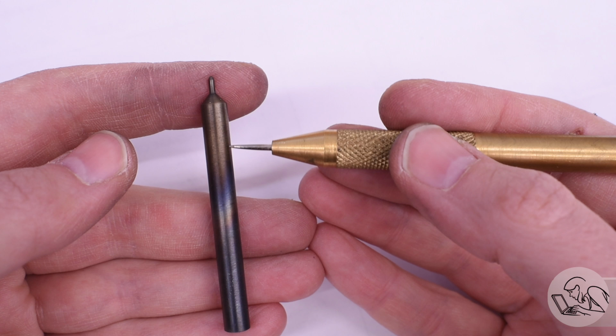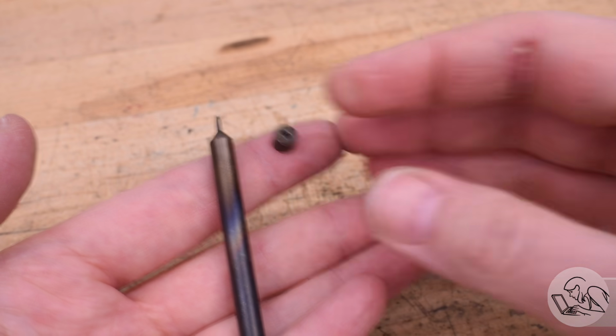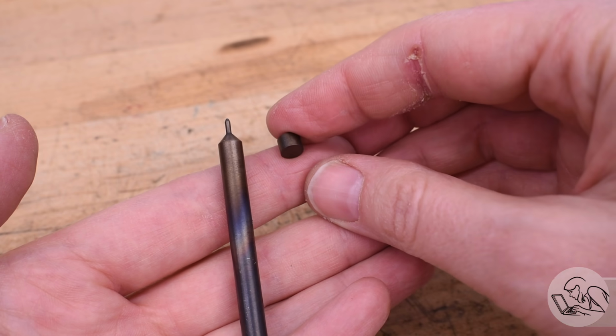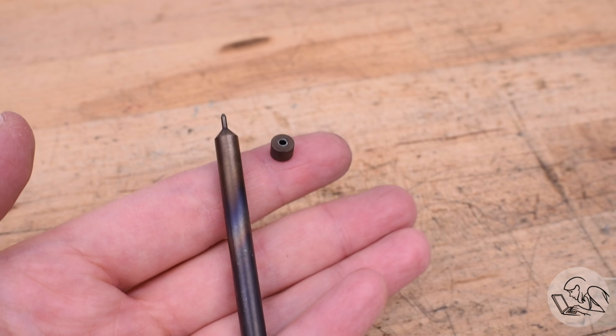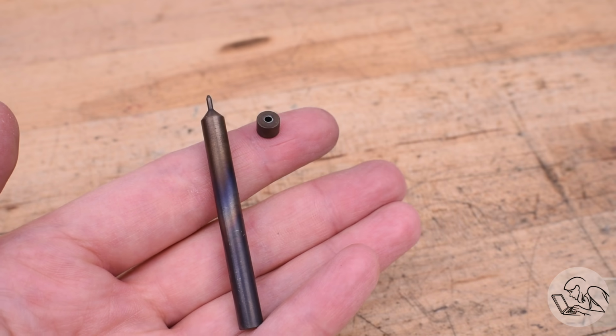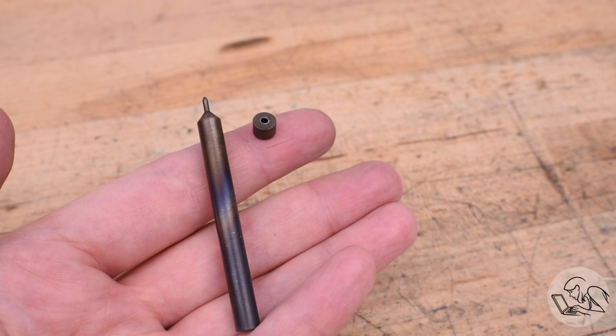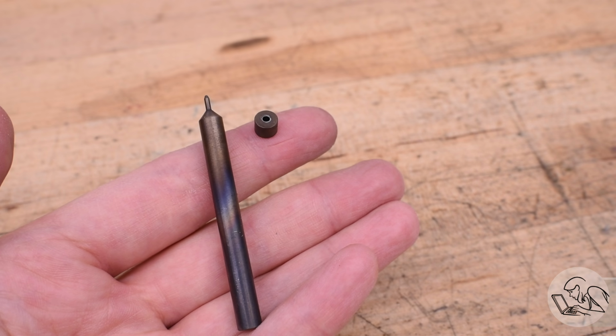So twist drills, screwdrivers, chisels, files, things like that are typically tempered from the tang or shaft end down towards the business end. You can see the die ended up pretty brown as well, so that's probably also slightly over-tempered. It's not a big deal for the die, which doesn't actually need to be that hard. The punch, however, I may have trouble with that, but we'll see. This is that heat inertia effect that I talked about. It's very, very easy to over-temper.